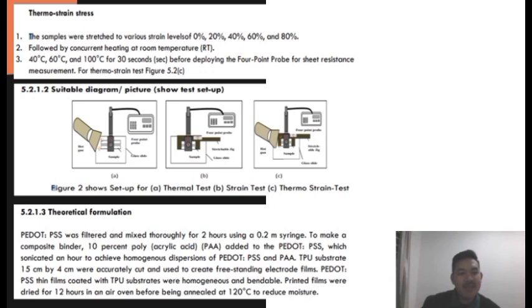For the thermal strain test, the procedure is that the sample was stretched to various strain levels, which are 0, 20%, 40%, 60%, and 80%, followed by concurrent heating at room temperature, at 40 degrees, 60 degrees, and 100 degrees for 30 seconds before deploying the 4-point probe. The first one is the thermal test, the second one is the strain test, and the last one is the thermal strain test.